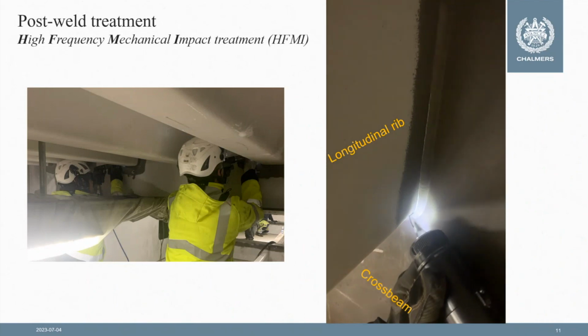That's in principle how this HFMI tool is working: very high frequency hits of this hardened pin on the weld toe region, causing very localized plastic deformation there. What we see here is a treatment of the weld between a longitudinal rib and a cross beam in an orthotropic bridge.